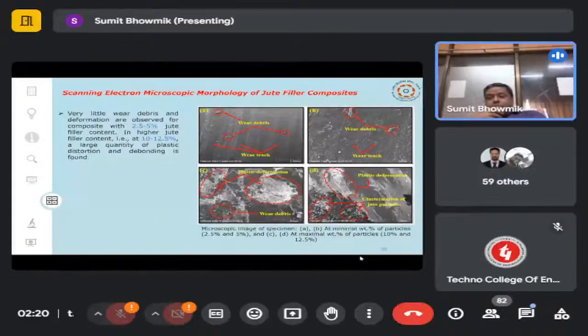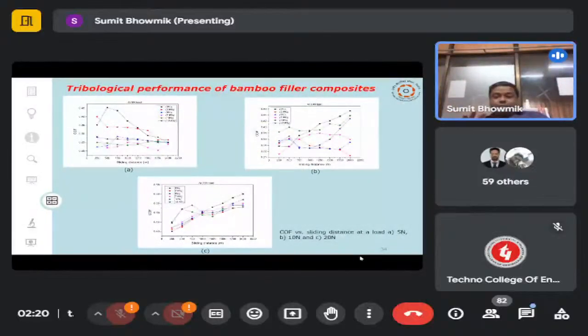Okay. So since this is to come out with a study, as an output parameter, not only from the result but the microstructural analysis also we have to consider. So this is the microstructural analysis of different filler debris and different worn surfaces of the component. These are the coefficient of friction results versus sliding distance at different loading conditions. If the load increases, the coefficient of friction also increases with the sliding distance.